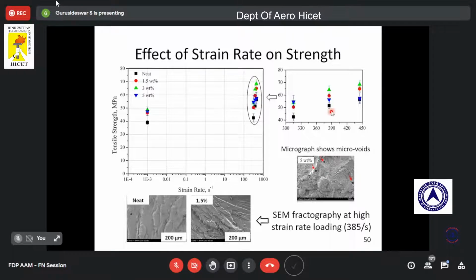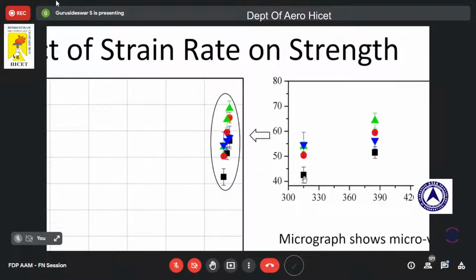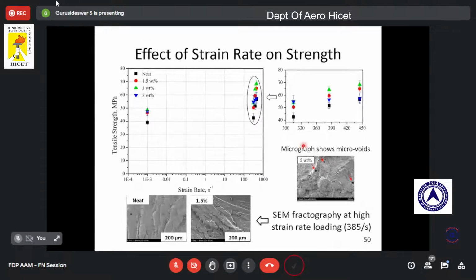But at the same time, we have got good improvement for lower clay loading. You can observe here, maybe you can zoom it. In this figure, black shows epoxy. So we have 40 megapascal as the strength, whereas red shows the 1.5%, where we have got 50 megapascal. So there is an improvement from 40 to 50. Again, for 3%, the green is showing 55. But again, for the blue, we were supposed to get good improvement, but we could not because of the micro voids. So this is what we observe for different epoxy clay samples, and the same trend has been followed for other strain rates.